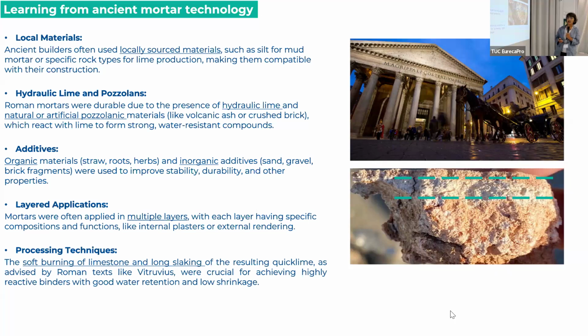mortars, which functions as a composite material, and this helps a lot to the final durable appearance and the consistency of the mortar. And an important thing is the soft burning of limestone and the long slaking of lime that resulted in materials with good water retention and low shrinkage.